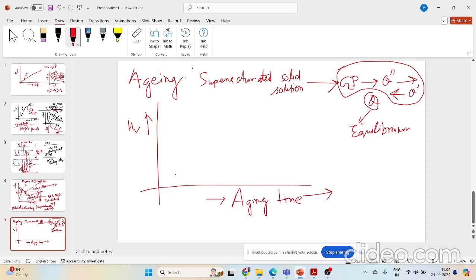Now, whatever I will be plotting right now, that has been found out from experimental observation, right? So I'll be plotting two different temperatures of aging. One will be at 190, one will be at 130. And there will be a difference observed in your hardness value for this GP region, theta double dash, theta regions, right? So one is this, which had been aged at 190 degrees,